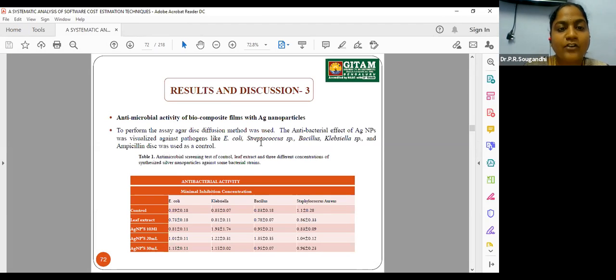So coming to the antimicrobial activity, the main function. The main application of this bio-nanocomposite film is food packaging. For food packaging, we have to see that food should not be spoiled and its shelf life should be increased. So for that, the first thing we have to see is its antimicrobial activity. If we see here, after the addition of the silver nanoparticles into the biopolymers, there is an increase in the activity. So if it is increased, we can use it for food packaging applications. It also has good barrier properties because of the presence of pectin and CMC.